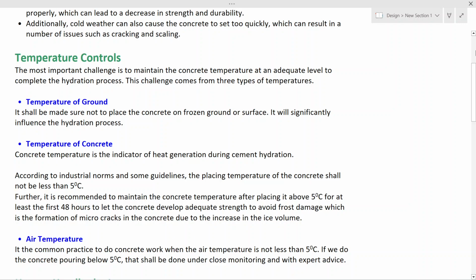Let's see what the temperature of the ground is. We shall make sure not to place the concrete on a frozen ground surface. It will significantly influence the hydration process. When it is frozen ground, the heat generated from the hydration process will be directly absorbed by the ground, so that there would not be adequate strength development because of this heat absorption, and there is no temperature rise in the concrete.